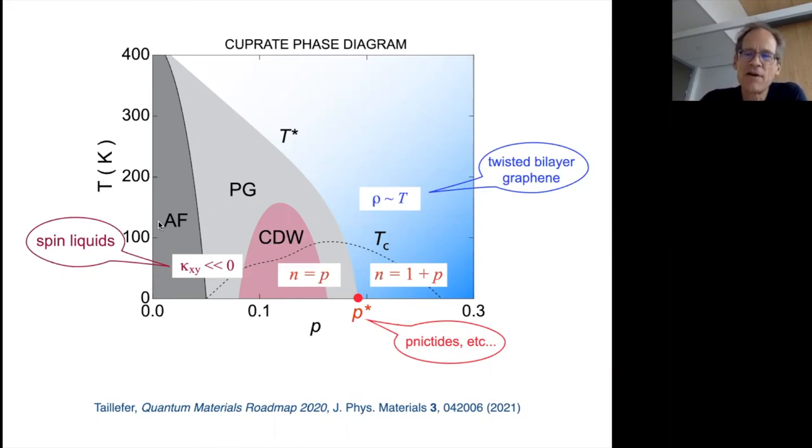The conditions, however, are sort of a theorem. They have what they call a no-go theorem. Basically, the spins have to have a chirality to them. In a Néel state, where you have collinear order on a square lattice, that's no-go. There's no chirality in that order. So then you ask, well, maybe the spins are slightly canted out of the plane and so on. Basically, theoretically, you would not expect it, but experimentally, the way we showed quite conclusively that magnons were not responsible for